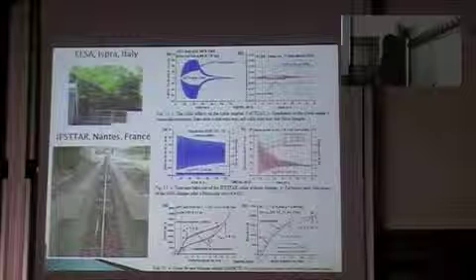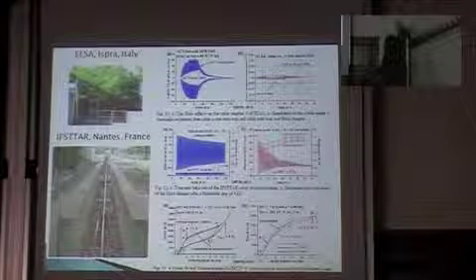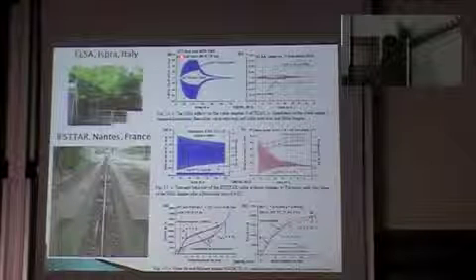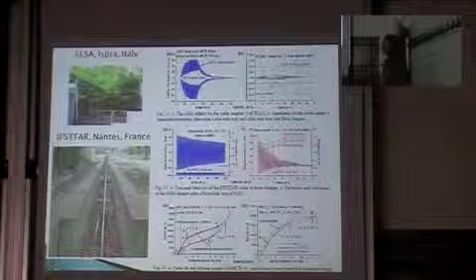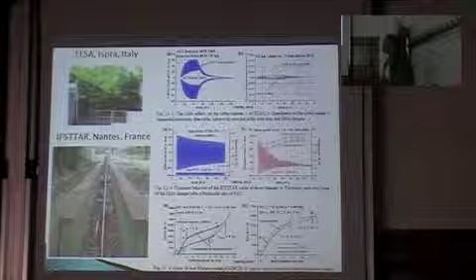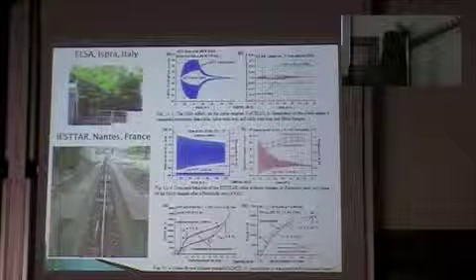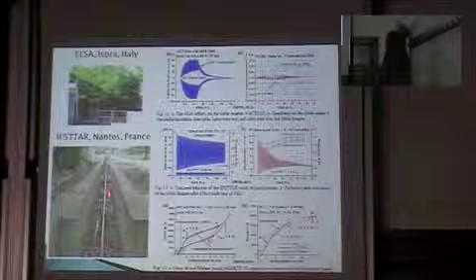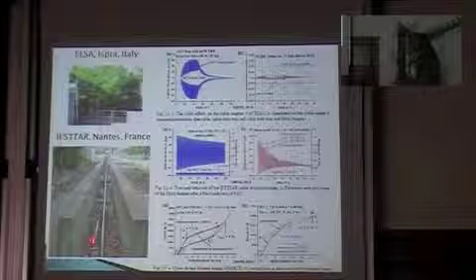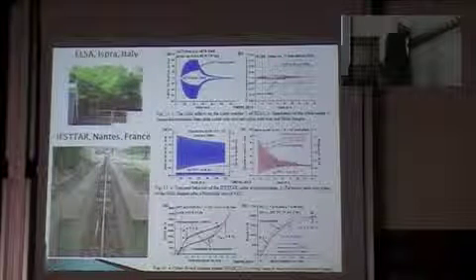And these are the results obtained from a bigger facility, which is the JRC in Ispra in Varese, where you can see that also in the case where there are no shape memory alloy devices inserted, there is a strong damping, which is not typical of cables, because usually cables have no damping at all. Why is that? Because these cables are full of wax. So we learned that they are already dampened. Instead, a cable which is not full of wax, so it has no damping, is the one in IFSTTAR Nantes, which is the LCPC. And you can see how there is no damping, or natural damping, occurring here.